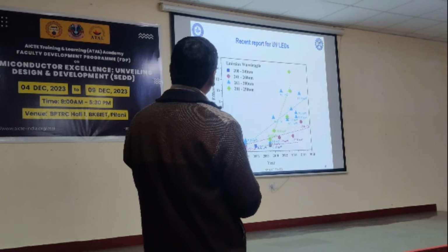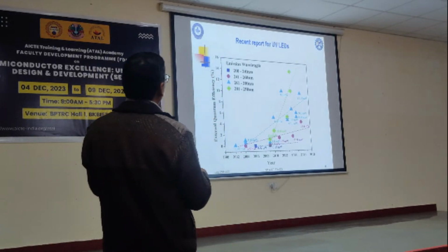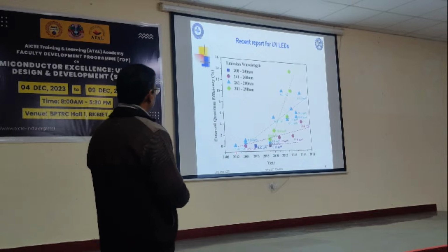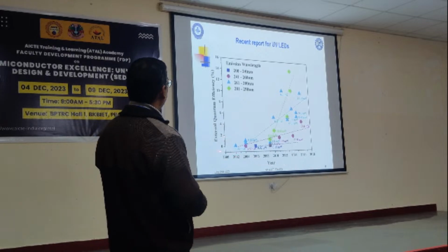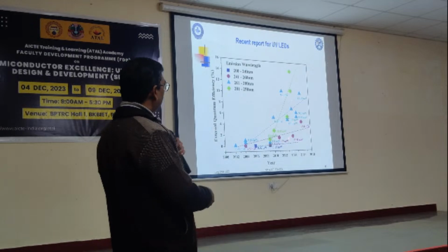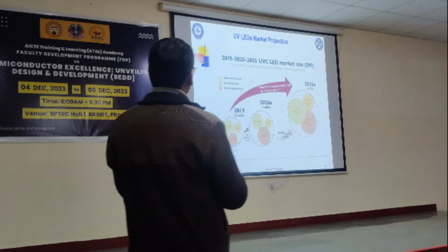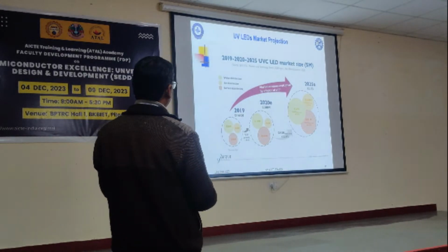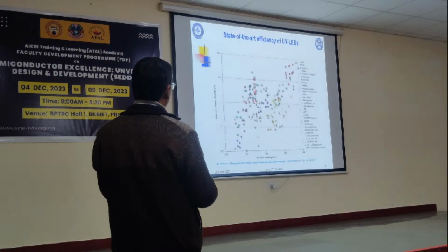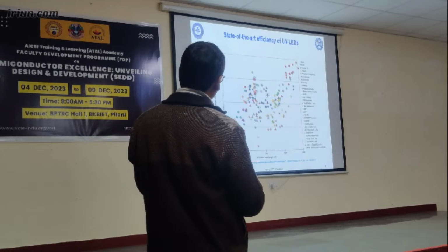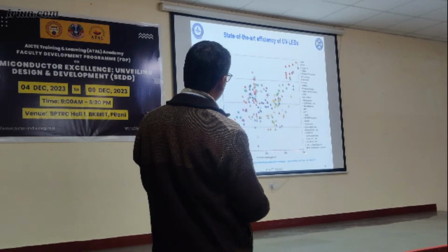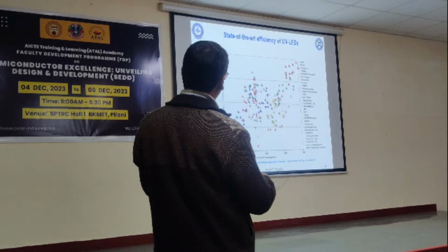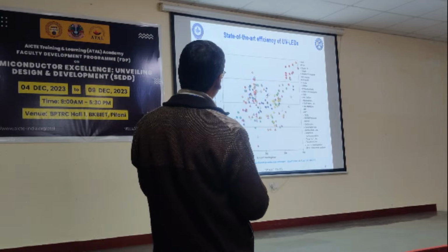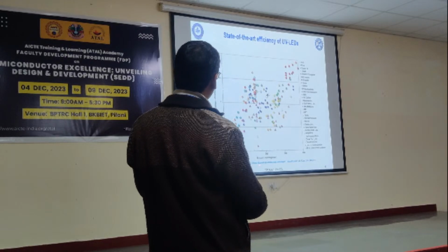What I mentioned is the area of UV LEDs, with the year and the quantum efficiency that has been achieved. With time, obviously the efficiency has increased, and if we see the market, it is a huge market for UVC particularly. This is the efficiency with wavelength. If we increase the wavelength, the efficiency is higher and higher, but where we need it much more, particularly in the UVC region, the efficiency is quite low, within 10% level, up to 300.